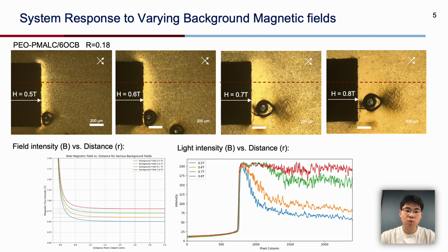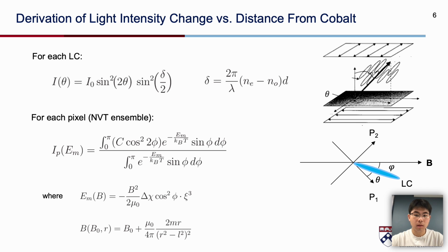We'll also try to describe how the light intensity varies with respect to the distance away from cobalt and under different background fields. So our basic idea here is we treat each pixel as an NVT ensemble, so the light intensity should follow, say, a Boltzmann distribution, which contains an energy term, and the energy term is a function of magnetic field. And the magnetic field is spatially varying here, so it's a function of distance away from cobalt and a function of background field. So in this way, we can relate the light intensity to the distance away from cobalt and the background field. But this formula needs to be further discussed in detail. If you have some ideas, you're welcome to reach out to me.